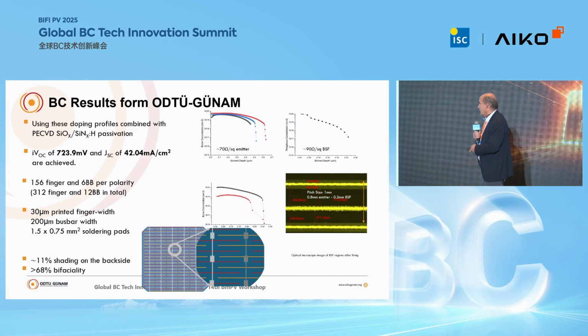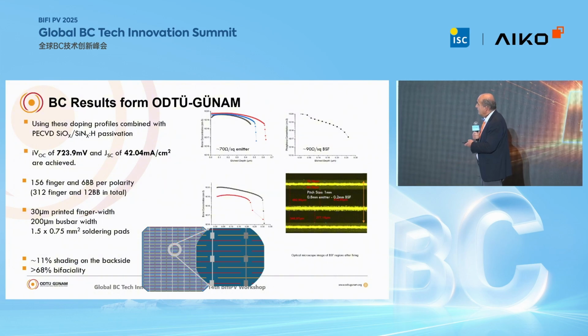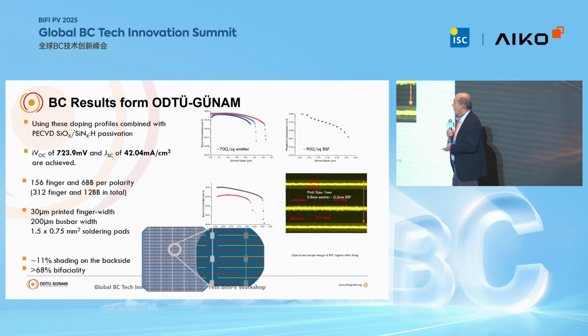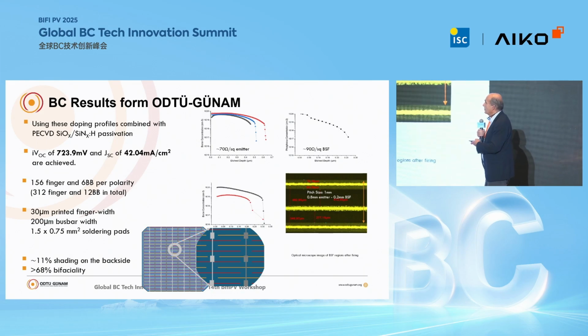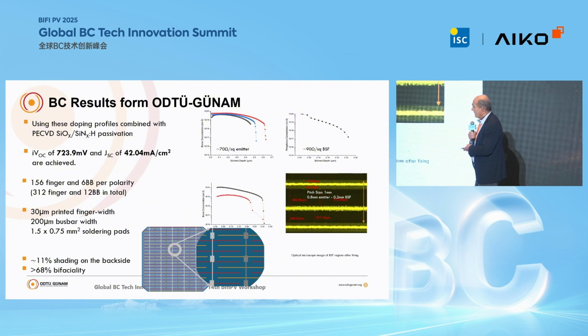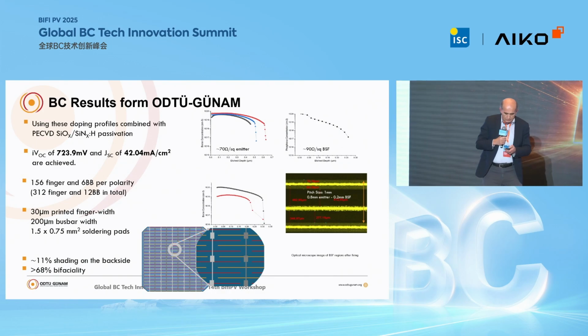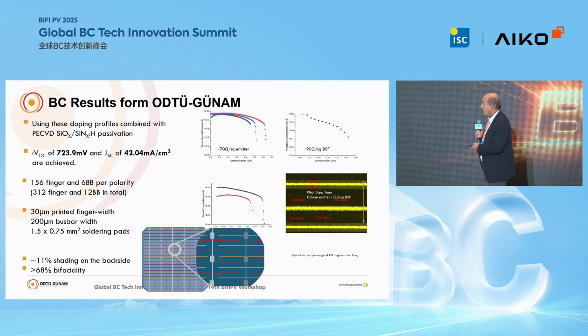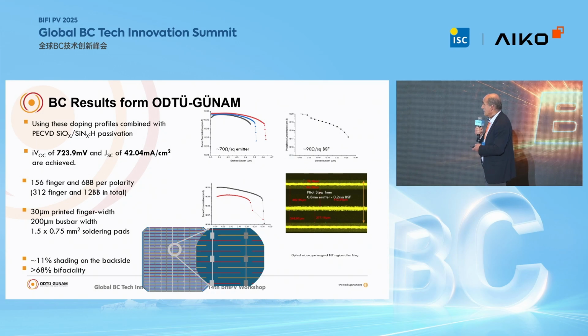So I want to show you this final slide. This is a BC cell we fabricated using a standard PN junction without any poly layer, so we have obtained good values for VOC and JSC, but the fill factor is low. But the good thing with this design is that we have very small shading on the backside and high bifaciality. We have stopped working on this because we are focusing on poly fingers and poly-based IBC solar cells.